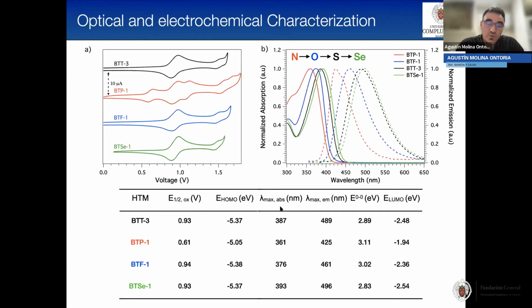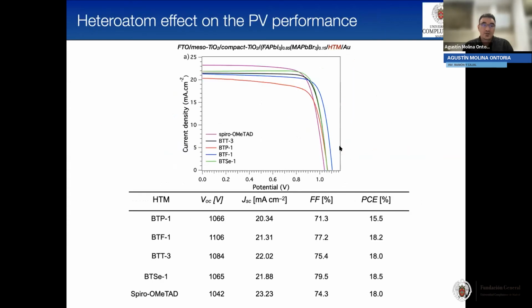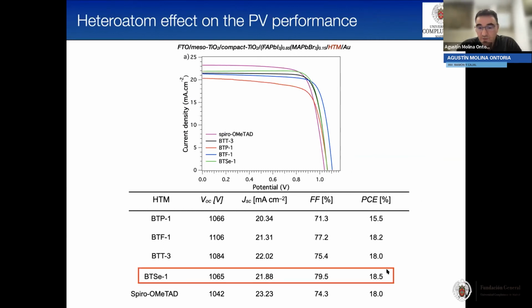From the optical characterization, we can see that the absorbance is redshifted in passing from nitrogen to oxygen to sulfur and finally to selenium. So again, from the intersection between the absorbance and the emission, we can obtain the optical bandgap, and then we can estimate the energy of the LUMO. So we prepared mesoporous devices using the mixed cation, mixed anion perovskite. And again, the best efficiency, 18.5%, was obtained in the case of BTSE with the selenium rings, showing an excellent fill factor, a current of 21.88 and a VOC of close to 1.07 volts.